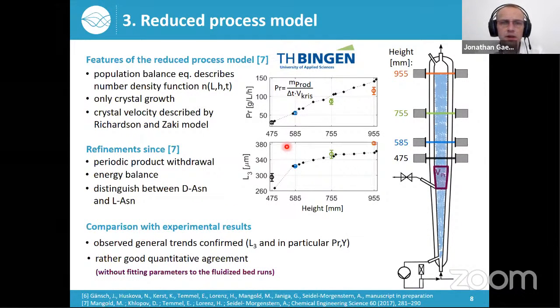Here you can see now the results as black dots, the calculated results from the reduced process model. What we can see is that all these calculated trends of the mean product crystal size and also the productivity and the yield can be confirmed by our experiments and also show a rather good quantitative agreement. Here I would like to mention that no parameter of this reduced process model has been fitted to these fluidized bed experiments.